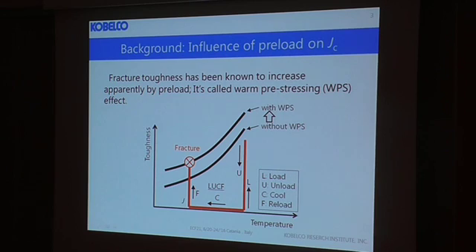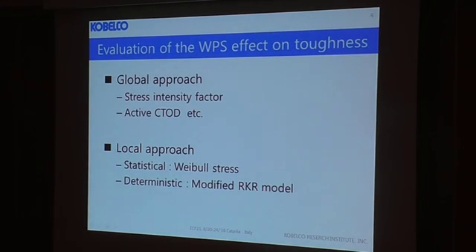Fracture toughness has been known to increase apparently by preload at a high temperature region, higher than the cleavage fracture temperature region. It's called the warm pre-stressing effect. Conventionally, the global approach had been used to evaluate the influence of preload. On the other hand, the local approach has been used recently. Weibull stress is one of the widely accepted methods.